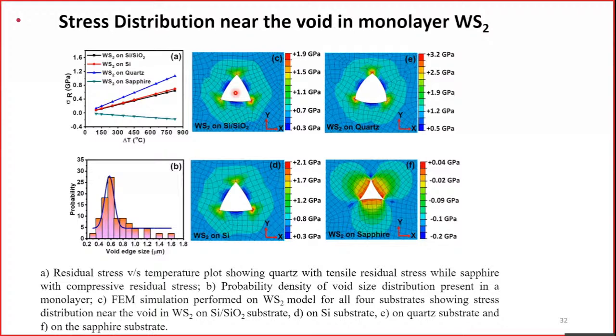We looked at both the thermal mismatch stress as well as the distribution around the void. Again, you can see that WS2 on sapphire is compressive in nature. So you will have a slight curvature in your void, but it will not crack. Whereas in other cases, the amount of stress is huge. We are talking about 0.7 to around 1.2 gigapascal of tensile stress contributing to fracture.